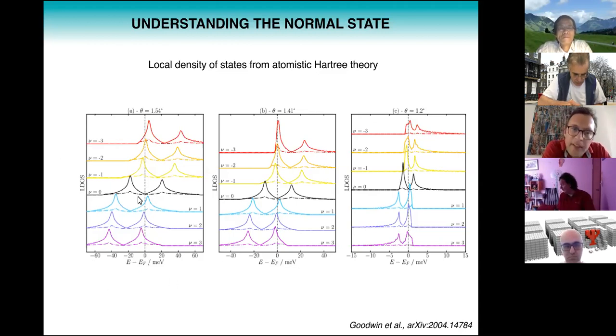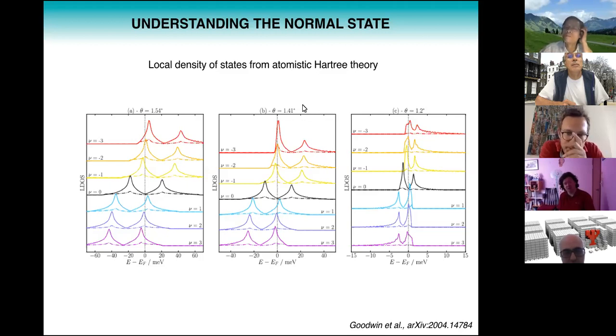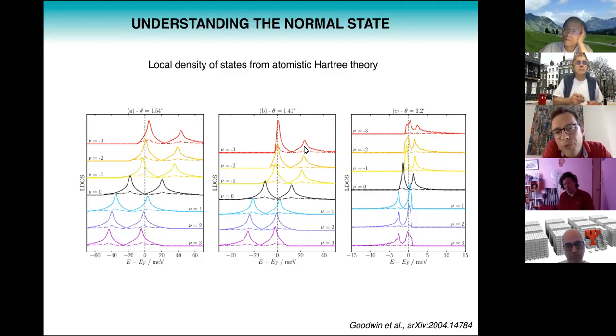And what we see is, well, we do get these Van Hove singularities, but they're quite similar. So there's not a lot of asymmetry in these Van Hove singularities. And you see that they more or less readily move past the Fermi level. So here we don't see any Fermi level pinning. Now, if we look at 1.4, you see already this is starting to change. If I look at the red curve, nu equals -3, you see that the Van Hove singularities are very asymmetric. And this electron-hole asymmetry is, of course, caused by Hartree interactions and is in agreement with experiment. And what you also see is now the Van Hove singularities don't move very readily past the Fermi level. So you start to see Fermi level pinning in the calculation as well.